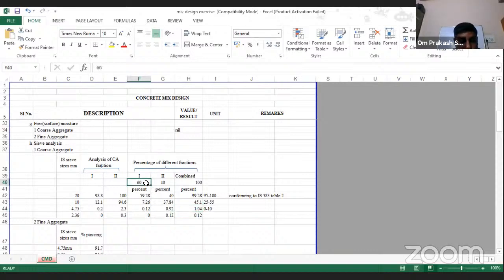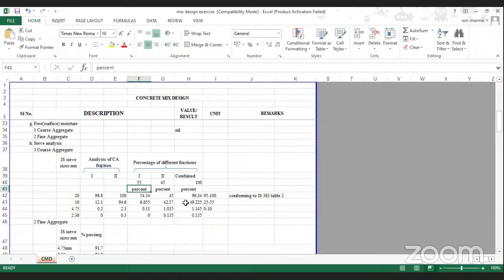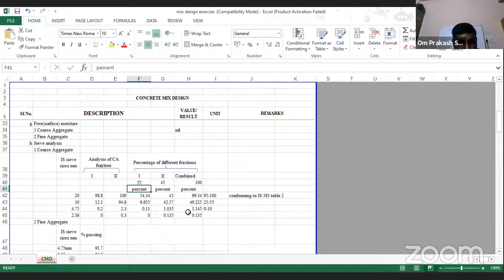Now, if I make this proportion 50-50, what will happen? See, on the 10 mm sieve size, the percentage passing is almost close to 55, 53.25, which is not good. So what do I have to do? I have to reduce the percentage of 10 mm. So I am making it 55. It is again 49, 1 and 0.135.